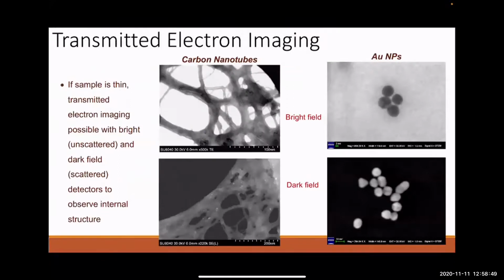If your sample is thin enough, it doesn't have to be, but if it's thin enough that you could put it into a TEM, for example, you can also do transmitted electron imaging by sticking a detector right beneath your sample.